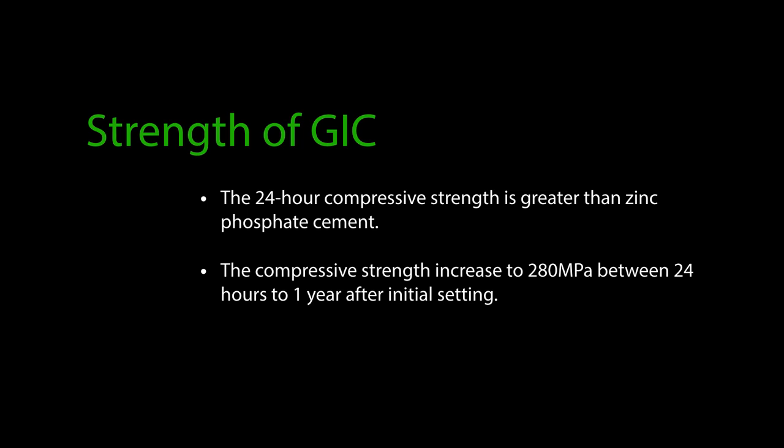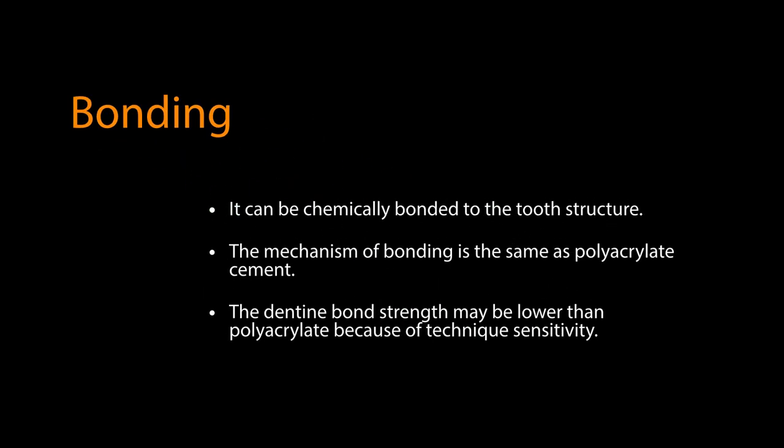The 24-hour compressive strength of GIC is greater than zinc phosphate cement, with compressive strength increasing to 280 megapascals between 24 hours and one year after initial setting. It bonds chemically to tooth structure — the mechanism of bonding is similar to polyacrylate cement. Dentine bond strength may be lower than polyacrylate due to technique sensitivity.